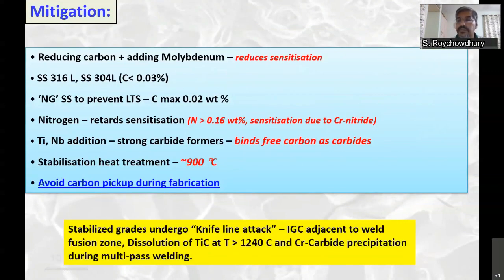Mitigation. Carbon being the responsible alloying element, reduce carbon to less than 0.03%. So we get the L grades. Addition of molybdenum to 2 to 3% again gives us this 316L grade, which is more resistant to sensitization. Addition of molybdenum reduces sensitization kinetics. Also, nuclear grade stainless steel still further lowers this carbon percentage to 0.02%.